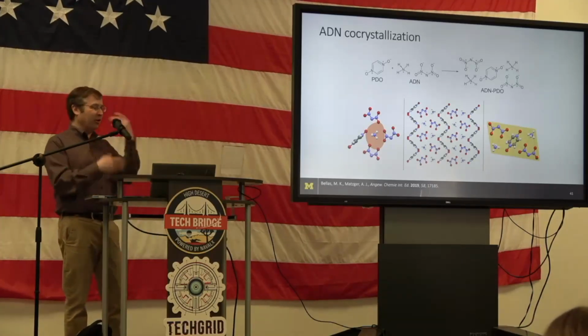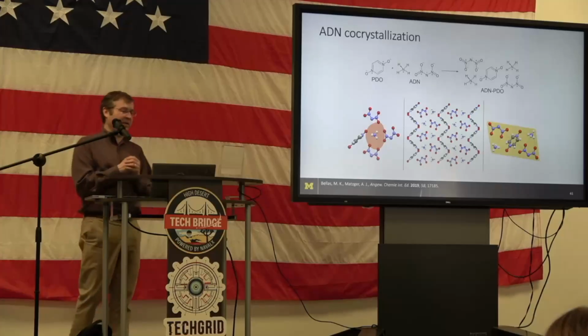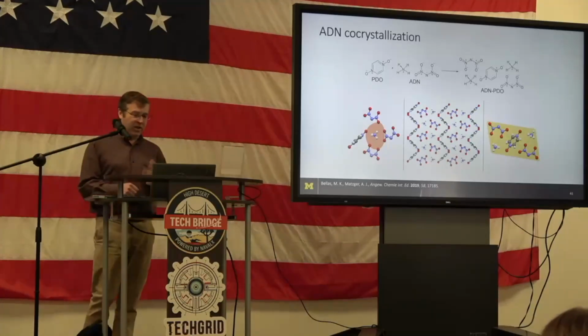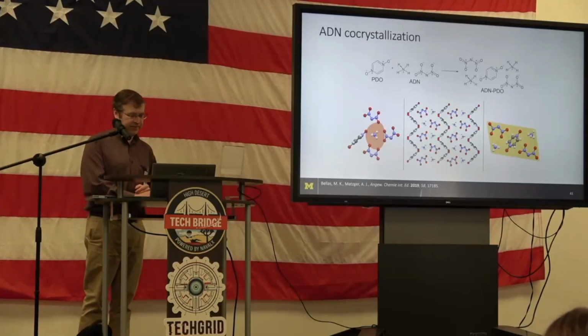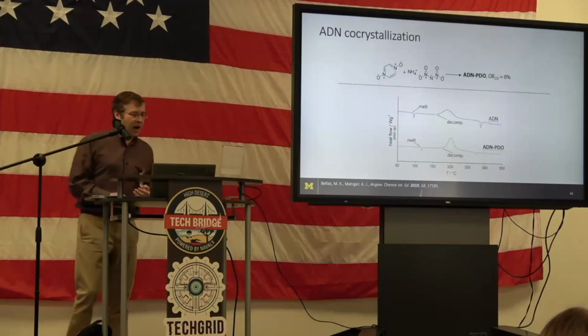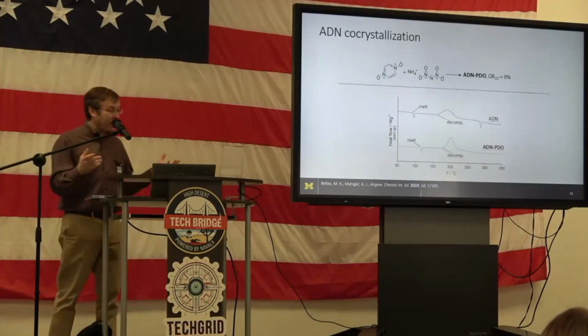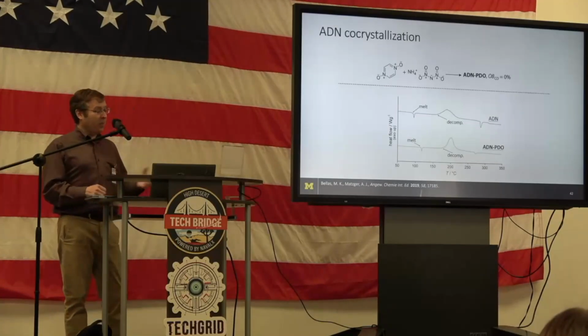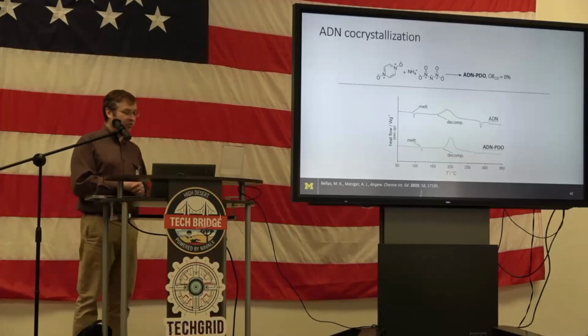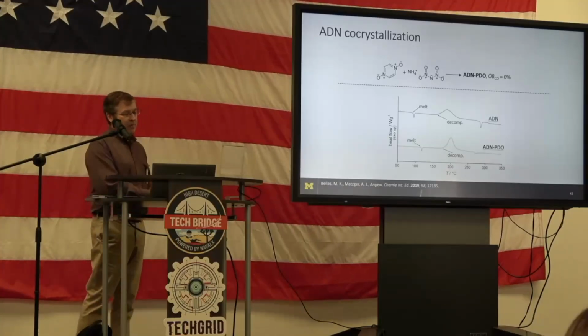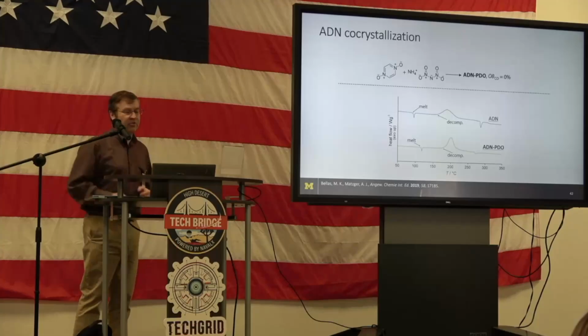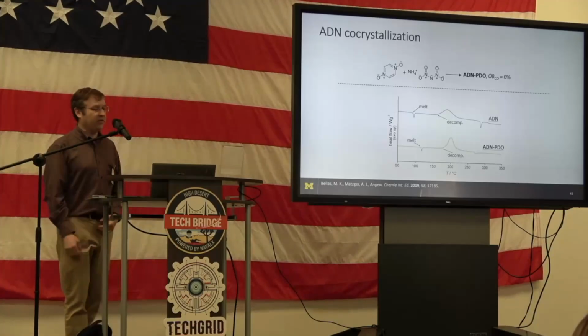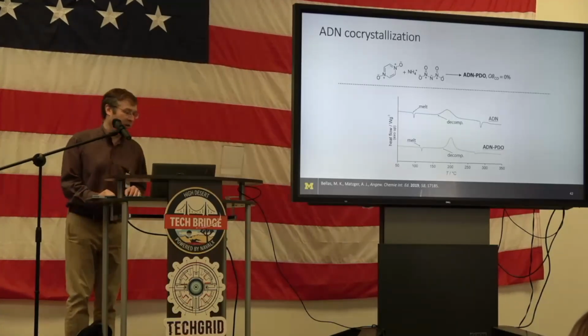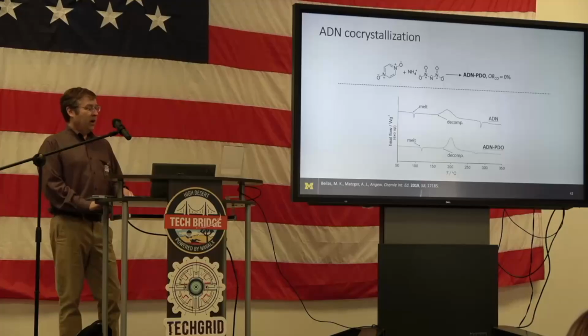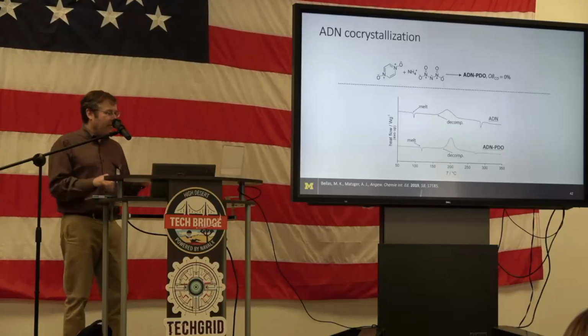And so this led us to a whole bunch of things I won't talk about today about lamellar architectures in salt co-crystals. The morphology was great. The oxygen balance, CO oxygen balance, was 0. And the melt temperature and decomposition were raised by a bit in this material as well. All right, so that's sort of the deep dive in the co-crystal.